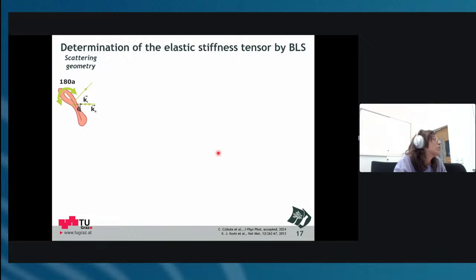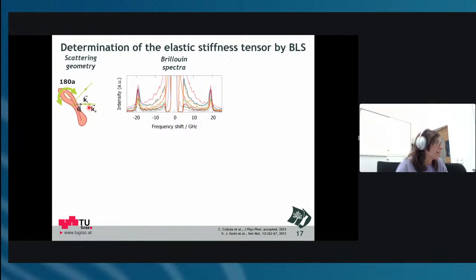Now some results of these scattering geometries and some further explanations. Initially I started out with 180 measurements because they are rather simple and it's easy to focus, because here you basically only need to control the beam in one direction. I obtained a few spectra on, for example, several flax fibers, 6 or 7, and on some I even measured 2 positions. As you can see, this is very repeatable even on natural fibers.